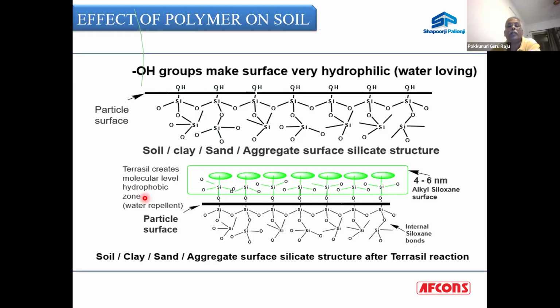Normally, you have OH groups, minus OH groups, which make the surface water loving in nature, hydrophilic in nature. And what this Terrasil does is it creates a bond with the OH group on the surface of the soil particles, and creates a nano alkyl siloxane bond, the SiO2, which is acting as a water repellent. The size or the layer of this particular particle is 4 to 6 nanometers.